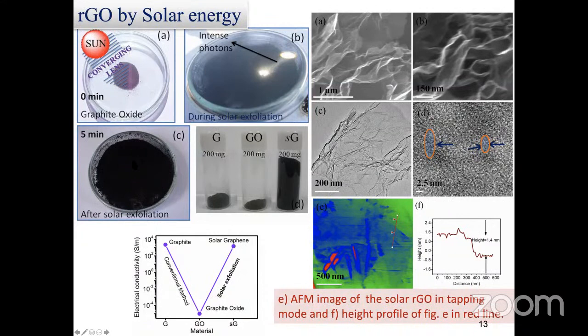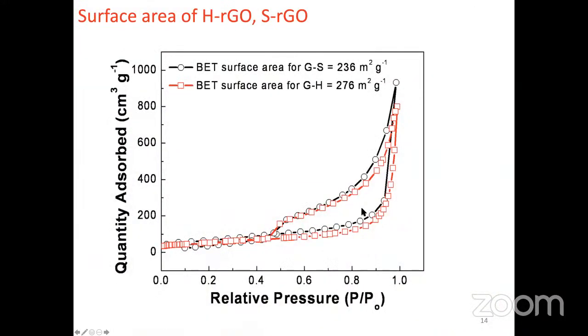So we can do the exfoliation such that all the functional groups which are reducing the conductivity are removed, so that one can get the electrical conductivity more or less on par with that of pure graphite. And here the specific surface area is very large, therefore one can use the solar graphene. I will come back to the video later on. If you see the video, then it's easy for you to understand. But the issue is that I cannot go out of this presentation. Now only it works.